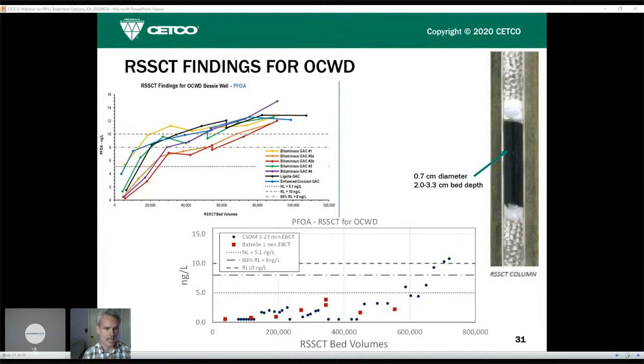So that's on the y-axis. And then again, on the x-axis, we have bed volumes. And these are simulated bed volumes because this was done in a rapid small scale column test setup. But you can see relative to some kind of metrics, California has low notification levels for PFOA and PFOS around 5 to 6 nanograms per liter. And then we have a baseline value of 10 nanograms per liter, and then 80% of that at 8 nanograms per liter. And from this top left figure, you can see that you typically see breakthrough of perfluoroalkyl acids in GAC systems around 60,000 bed volumes. And this is a trend that I've seen in pilot scale studies as well with contaminated groundwater.